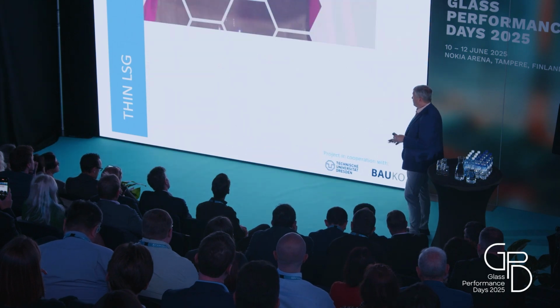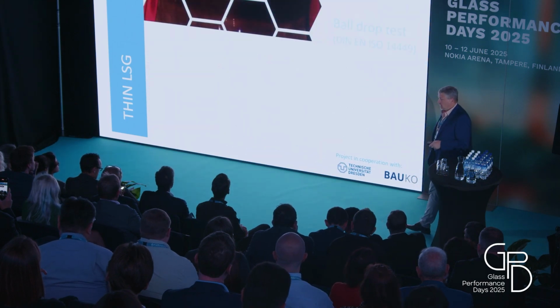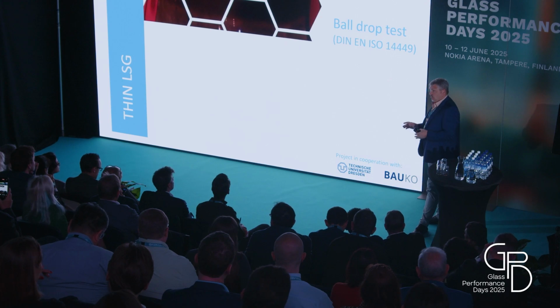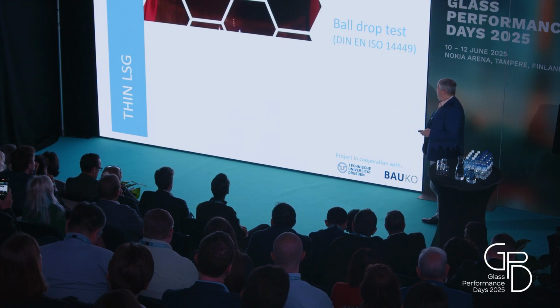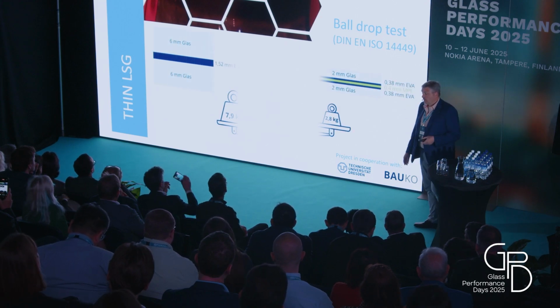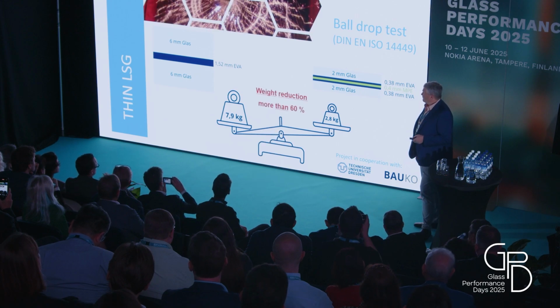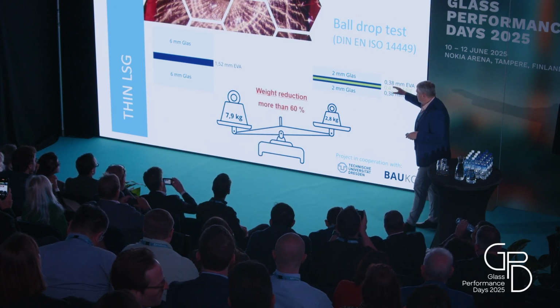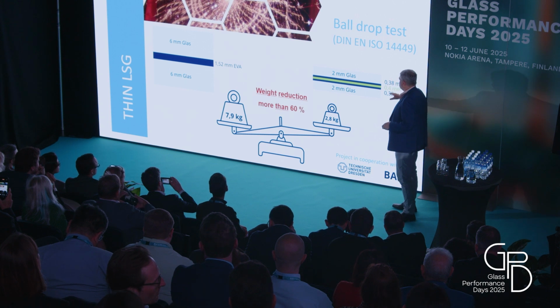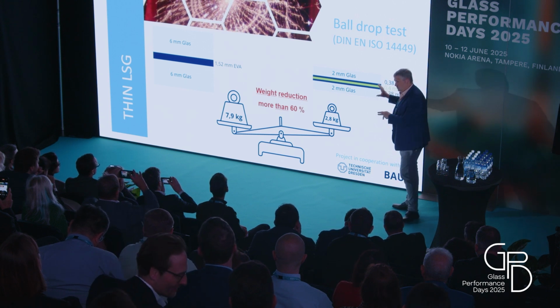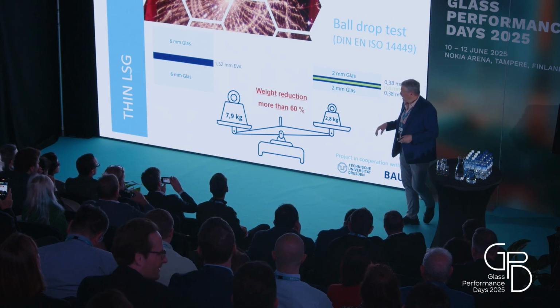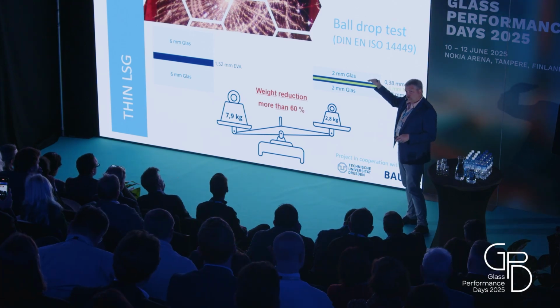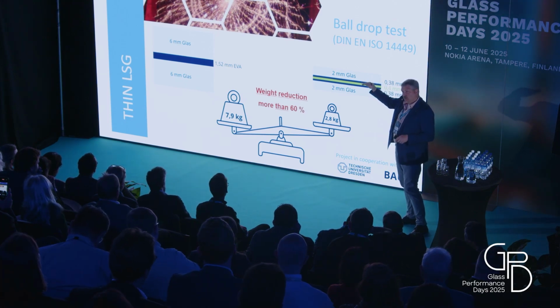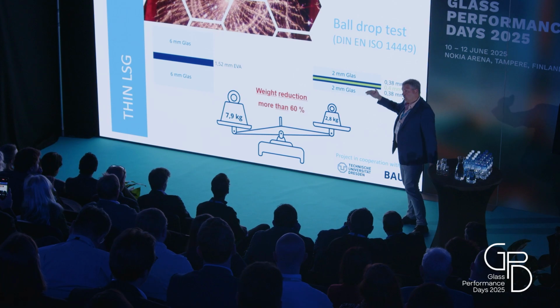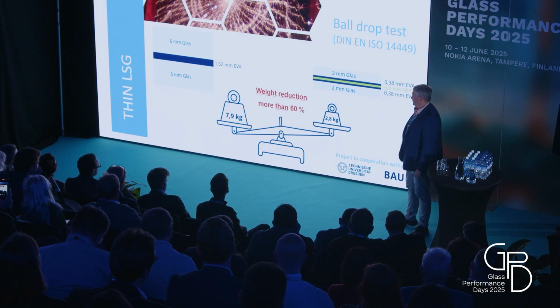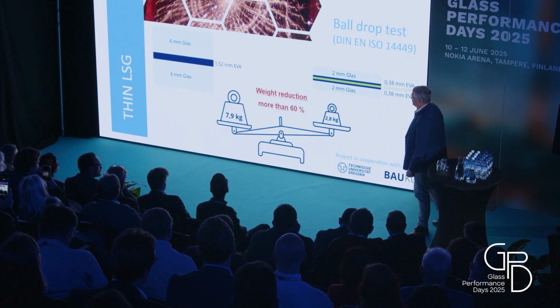Some results of this project are shown here. We have selected the ball drop test following EN 14449. We have done constructions with different kinds of interlayers with thin glass. In this case, I'm showing only 2 millimeter glasses. We have chosen a certain height in the ball drop test and have checked what is possible compared to normal standard safety glass, as you can see on the left side.